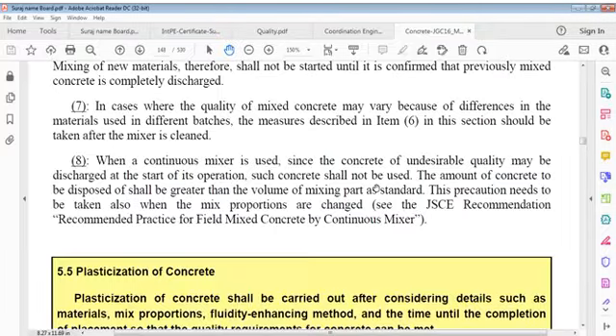In cases where quality of mixed concrete may vary because of differences in materials used in different batches, measures described in this section should be taken after the mixer is cleaned. When a continuous mixer is used, since concrete of undesirable quality may be discharged at the start of its operation, such concrete shall not be used. The amount of concrete to be disposed of shall be greater than the volume of the mixing part as standard.